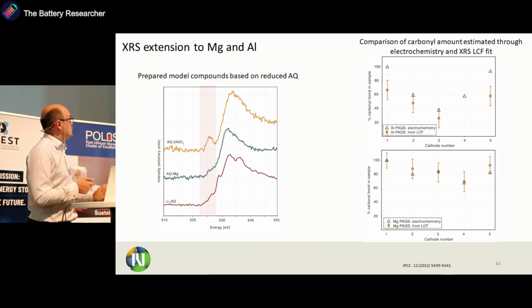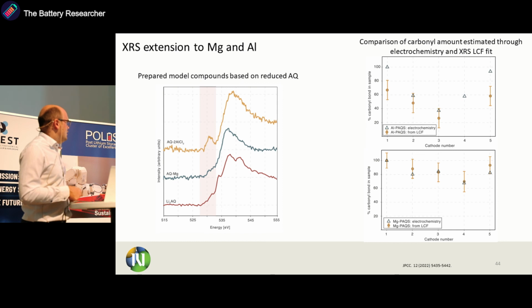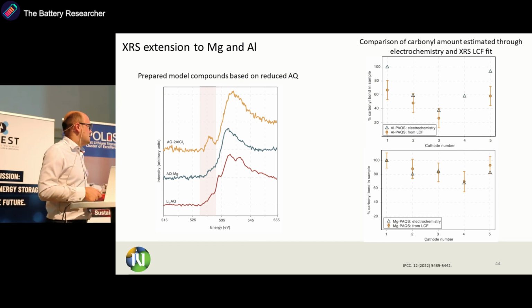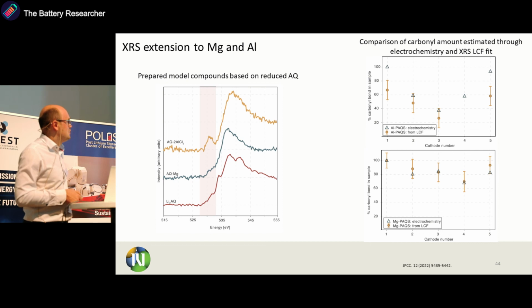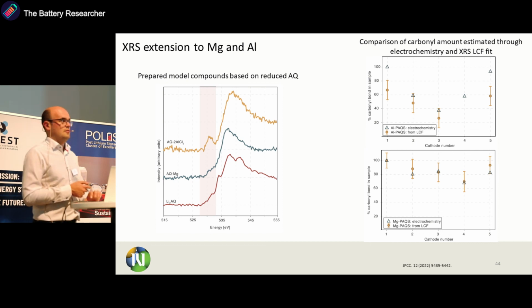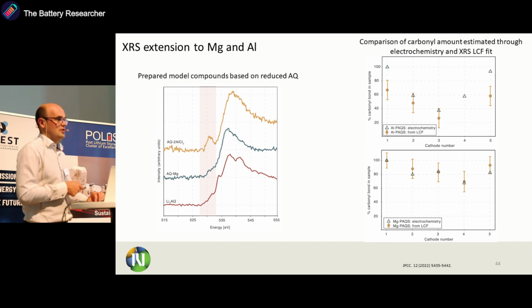We extended this also to the magnesium and aluminum. So first by preparing model compounds. So here is lithium salt, magnesium, and aluminum, and then doing the correlation. Although we have to say that this correlation is quite good between the electrochemistry and XRS in magnesium, but not as good in the aluminum. But this might be also connected with the fact that we did not synthesize the best model compound.